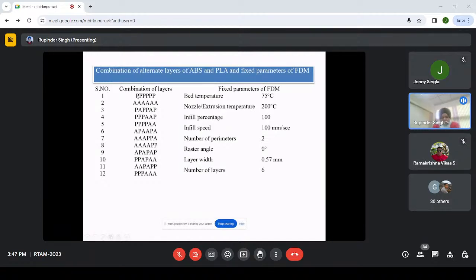So what we actually varied was, in the first experiment, all layers were of a single material called PLA. So you can see first PLA layer, second PLA, third PLA, fourth, fifth, sixth, all layers were of the PLA. Then in the second case, all layers were ABS. Then we used the concept of the random number, and from 3 to 12, some random combinations like PA, PP, AP, this combination was printed. Now, what does this mean? First layer of PLA, second layer of ABS, then two successive layers of PLA, then ABS, then PLA.